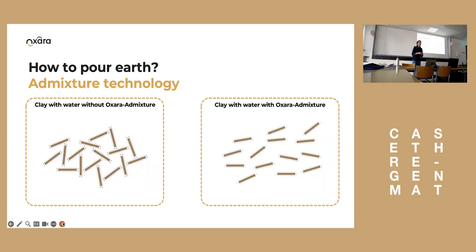And the way that can work is, going back to these clay platelets, they have a surface charge. On the edges they are charged positively, and on the sides negatively. In a normal state, the positive charges are attracted by the negatives, and the clay platelets arrange in a card house structure. In this way, they can also have a lot of water in between. Then if you introduce a dispersant, an admixture that can change the surface charge on the edge from positive to negative, the edges get repelled and they disperse. If they're oriented in this parallel way, they can much more easily slide past each other. And then you can have a higher fluidity with the same amount of water. That's the principle of the admixtures we are using.